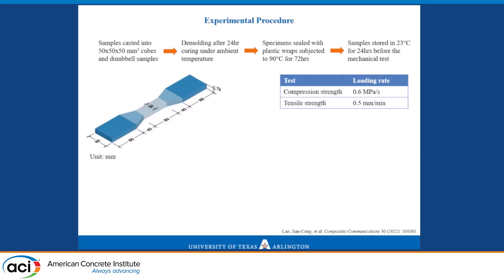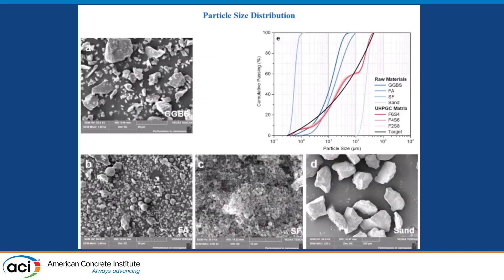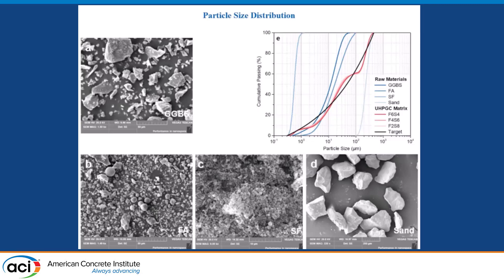The curing is standard for geopolymer: you need 90 degrees Celsius for 3 days before and after curing, as shown in the curing diagram. We also used silica fume for optimizing the particle size distribution. The particle packing is shown here — sand, slag, fly ash — and the red line is the theoretical particle packing concept already used for UHPC. What was achieved is very close to the theoretical curve. SEM images of sand, fly ash, slag, and silica fume are also shown.